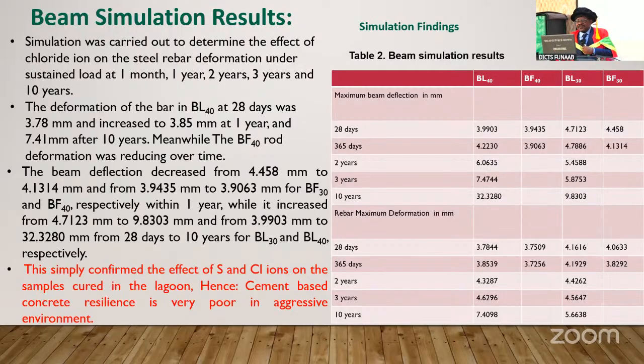For the deflection in beam, the deflection decreased from 4.45 mm to 4.13 and from 3.94 to 3.90 for the BF40 and BF30 respectively within 1 year, while it increased from 4.7 to 9.8 and from 3.9 to 32.32 from 28 days to 10 years for the BL30 and BL40 respectively. This simply confirms the negative effect of sulfate and chloride ions on the sample cured in the lagoon water. Hence, cement-based concrete resilience is very poor in aggressive environments.